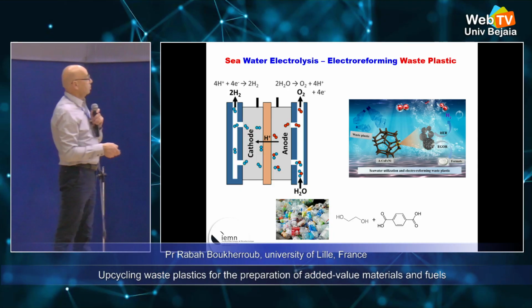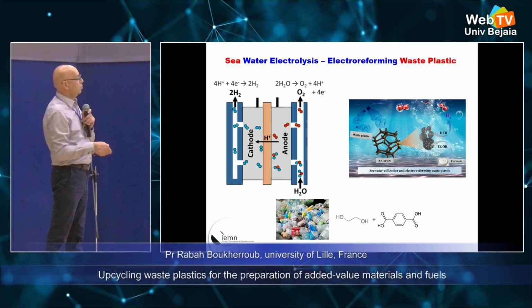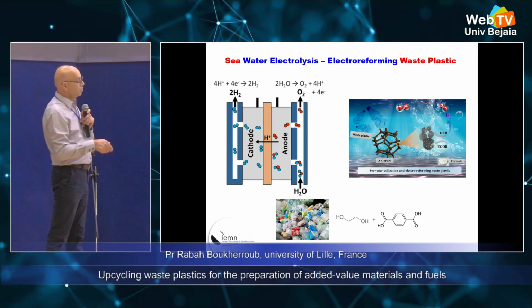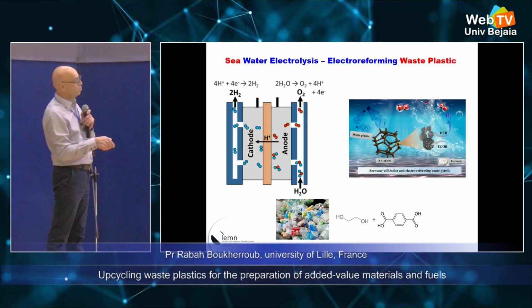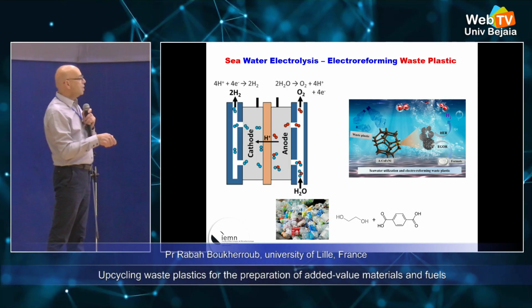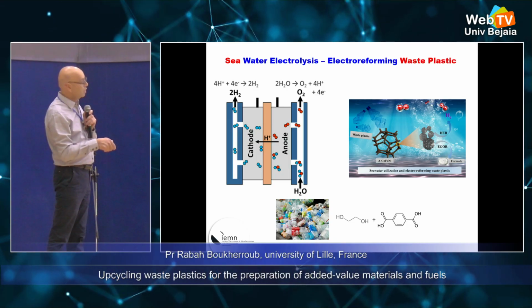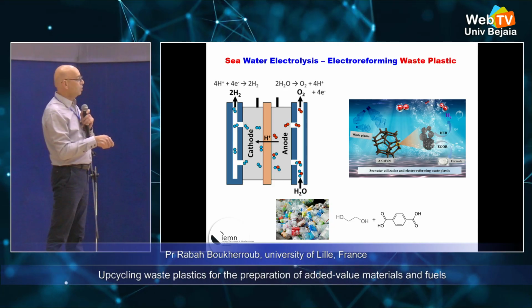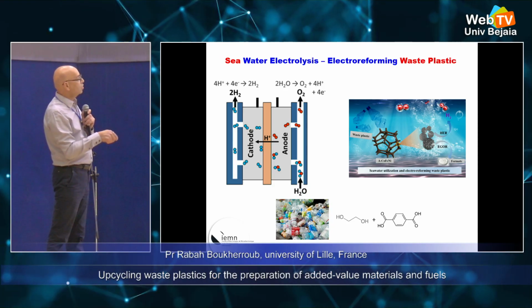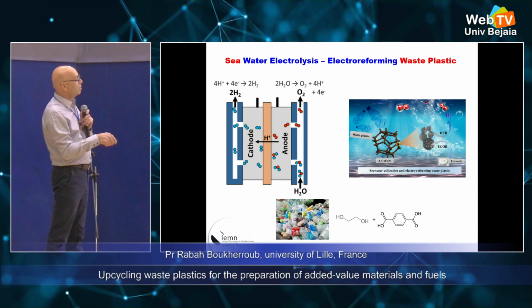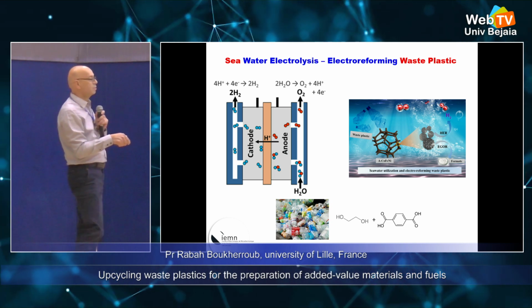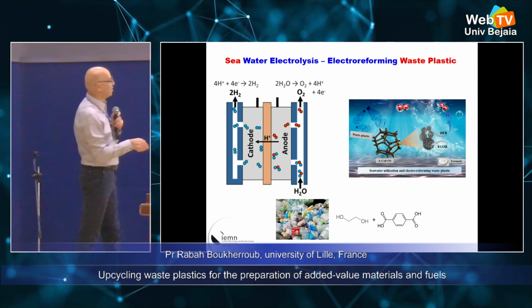Previously, what we did with the plastic, if you remember, is we hydrolyzed it. So this acid, we used it to make MOFs, and then we transformed the MOF with a laser. Now, what I want to do is to use this ethylene glycol as a chemical and replace the oxygen evolution here. I will oxidize it and make formic acid out of it.